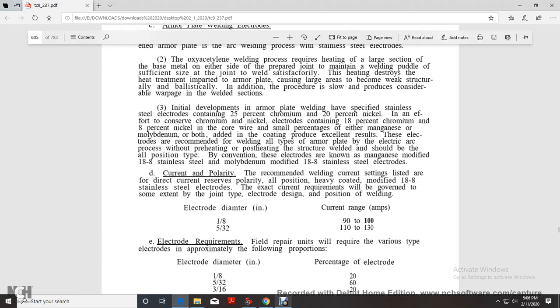Initial development of armor plate welding specified stainless steel electrodes containing 25% chromium and 20% nickel, and later a conserved chromium and nickel electrode containing 18% chromium and 8% nickel. The core wire has a small percent of either manganese, or molybdenum, or both added, with the coating. The excellent results of these electrodes recommend them for welding all types of armor plate with the electric arc process, without preheating or post-heating of the weld structure. They are the conventional electrodes known as the manganese modified 18-8 stainless steel and molybdenum modified 18-8 stainless steel electrodes.